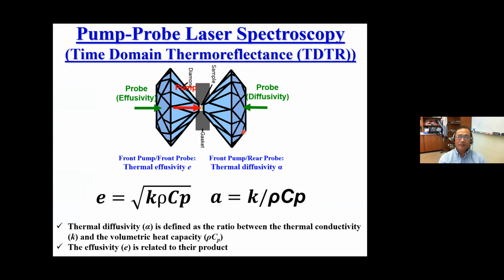So for the thermal conductivity measurements, we use pump and probe laser spectroscopy, or to be more precise, the time domain thermoreflectance technique. There are two ways that you can actually probe the thermal conductivity. So let's say the red arrow here is our pump laser, and you can probe from the front side or from the back side. To be more precise, we are not really probing the thermal conductivity. In this geometry here, we are actually probing the thermal effusivity. In this geometry here, we are probing the thermal diffusivity, and they are related to the thermal conductivity through these